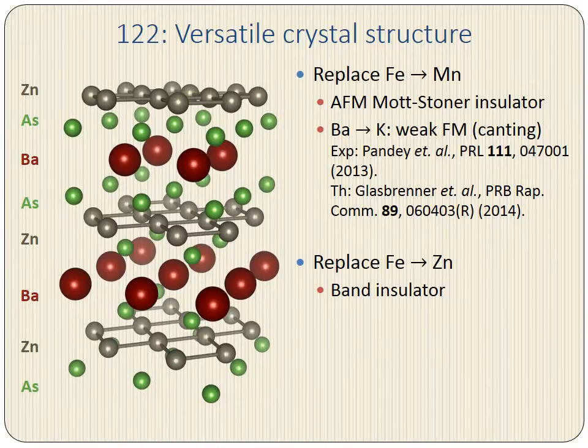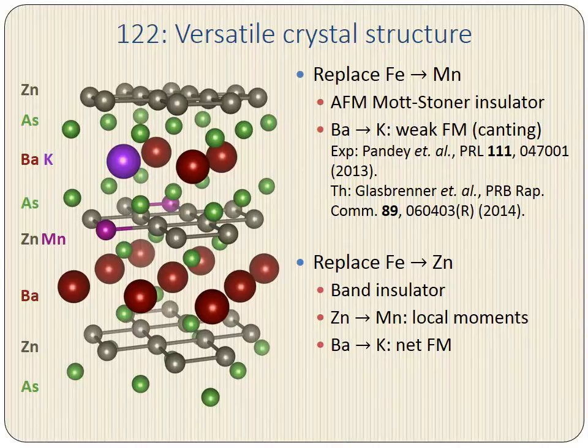Even more interesting is if you replace iron with zinc. You end up with barium zinc arsenic, a band insulator in density functional theory, and a semiconductor in experiment. You can then create a dilute magnetic semiconductor by doping it with manganese, and then you can induce a net ferromagnetism by hole doping it with potassium.